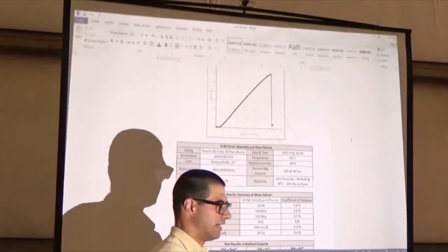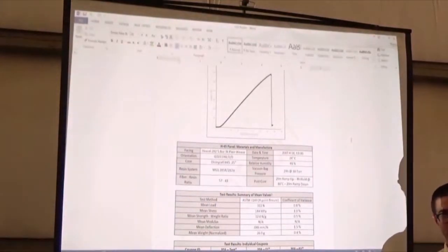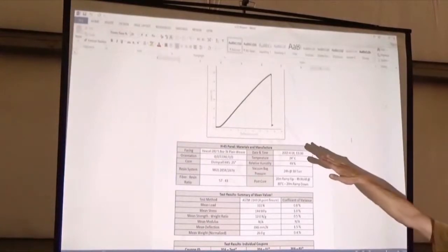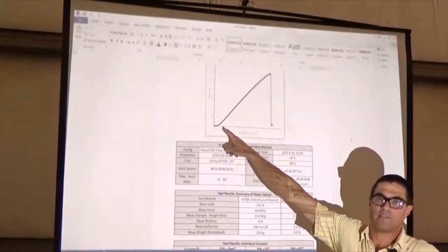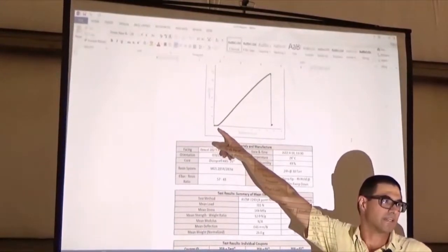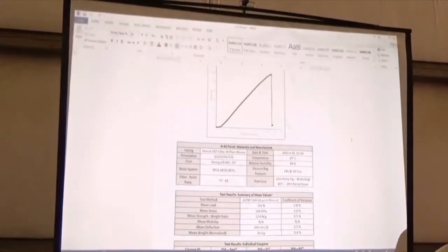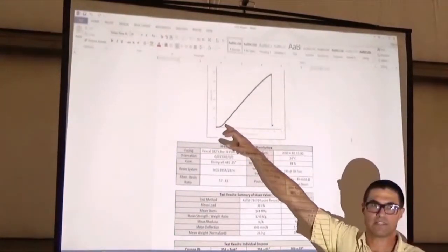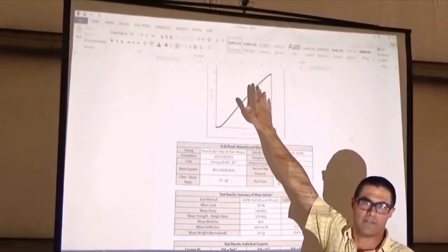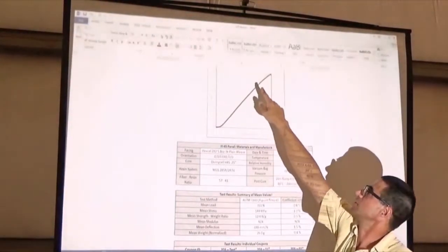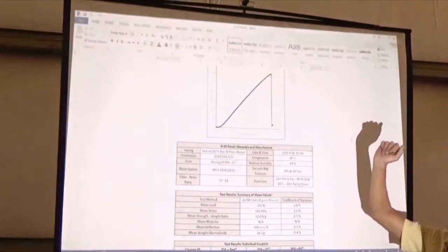I looked at Divinycell 45, 60, 80, 100, and then Rohacell IGF 51, 71, 110, and honeycomb. I was trying to learn what's the difference between these different foam cores. So this is a typical plot. You get a little bit of a curve here, and that's compliance. The whole system is kind of settling in, and you get a little bit of force, but it's not linear. Then you have a linear region, and then at the very end, when it begins to fail, it starts to go nonlinear, and then you have a failure.